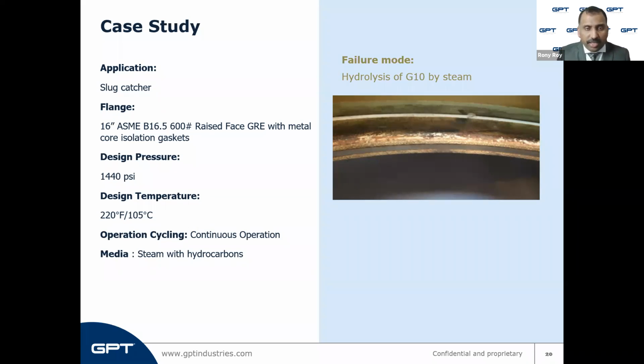Hydrolysis, as it is known in Greek terms, hydro means water and lysis means to unbind. The epoxy chains were broken down under pressure and it literally got driven out of the glass matrix. This dramatically reduced the strength of the product and ultimately led to the leakage or blowout.